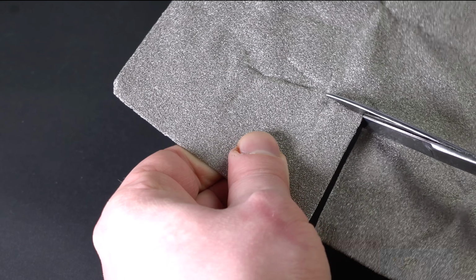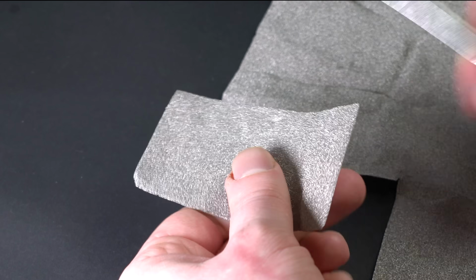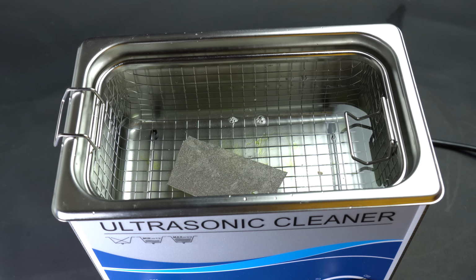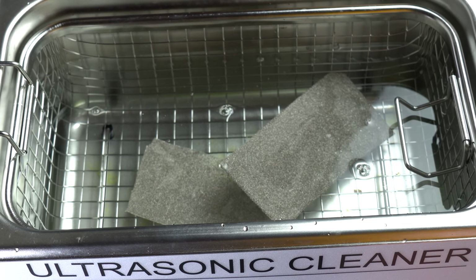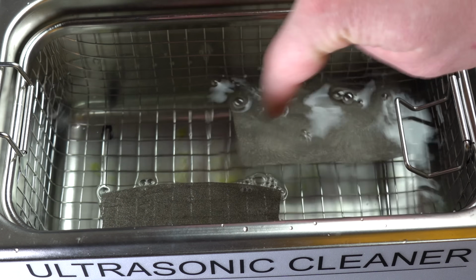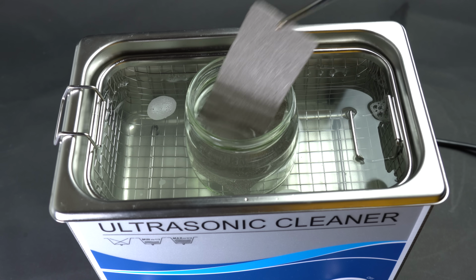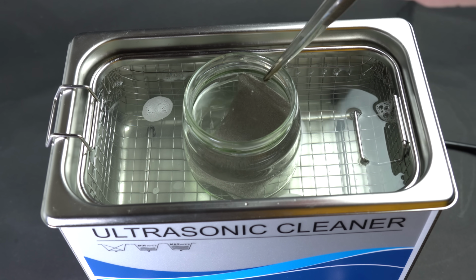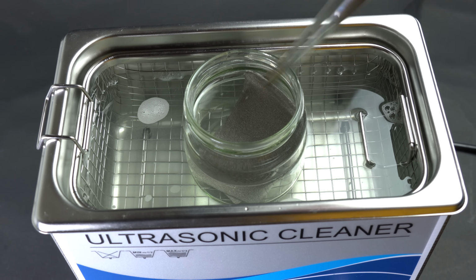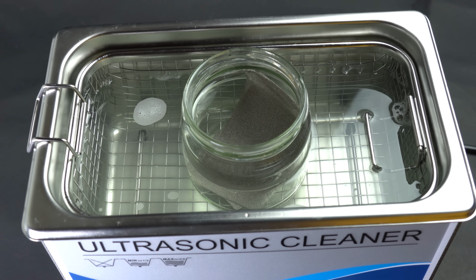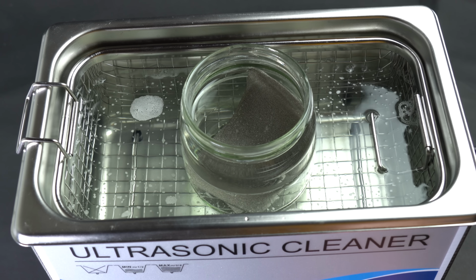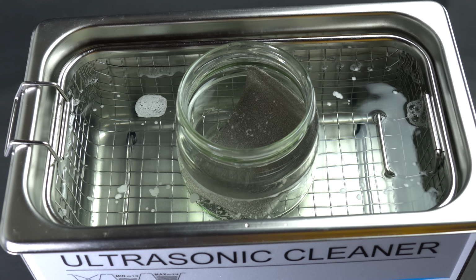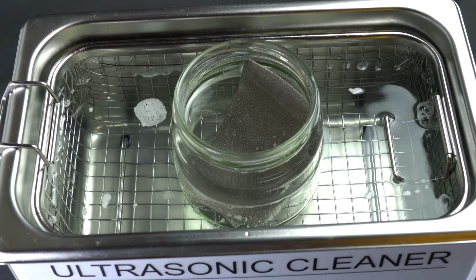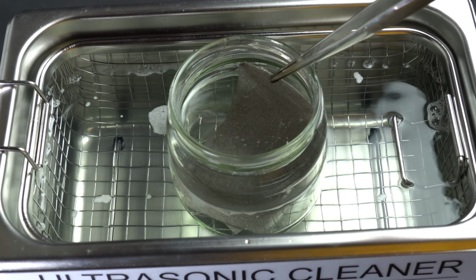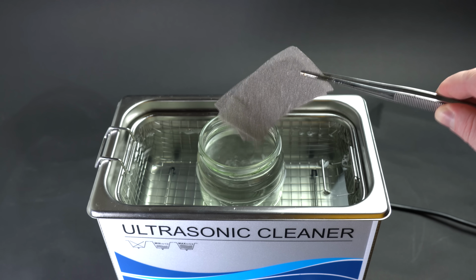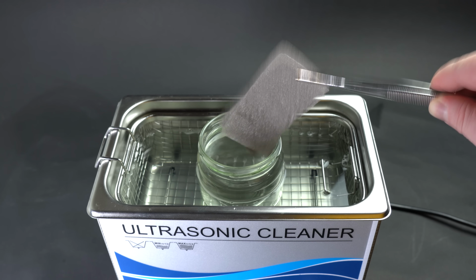Before going platinum plating, we need to remove grease and prepare the surface of the nickel sheet, which is why first I lowered strips of the nickel sponge into an ultrasonic cleaner filled with soap solution. After cleaning nickel for 10 minutes, I am lowering these strips of nickel into a 50% alcohol solution in order to remove vestiges of soap and dirt. When running ultrasonic cleaning, cavitation bubbles are released. Make sure that all the dirt is removed from the pores of the nickel sponge. When the strips dried, I got two clean electrodes.